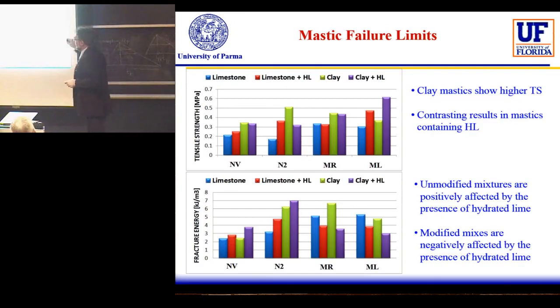Now we are looking at what's happening in the mastics. Here is the result of the test on the mastics, and we can see a clearer behavior. The clay mastics show, in general, a higher tensile strength than the others. It's something that was possible to see in the mastic and not in the mixture. The hydrated lime still has an unclear behavior. In terms of fracture energy, the unmodified mixture appears to benefit from the presence of the hydrated lime. On the other side, the mixture with polymer modified bitumen appears negatively affected by the hydrated lime.